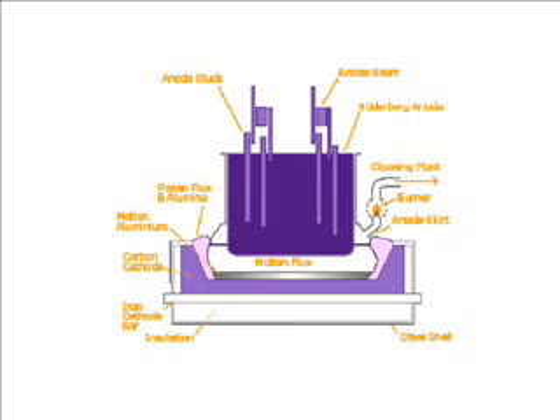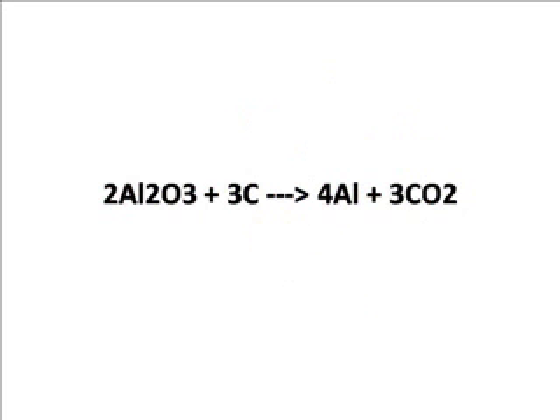This mixture is then heated to about 980 degrees. The mixture is then melted and the refined alumina is added. This then dissolves in the molten electrolyte. The hot molten mixture is electrolyzed at a low voltage of 4 to 5 volts, but a high current of anywhere from 50,000 to 280,000 amperes. This process reduces the aluminum ions to produce molten aluminum metal at the cathode.